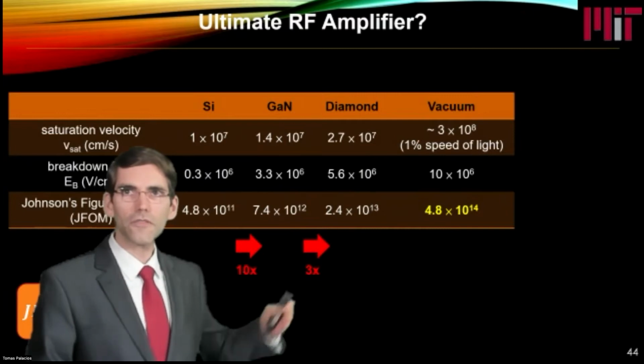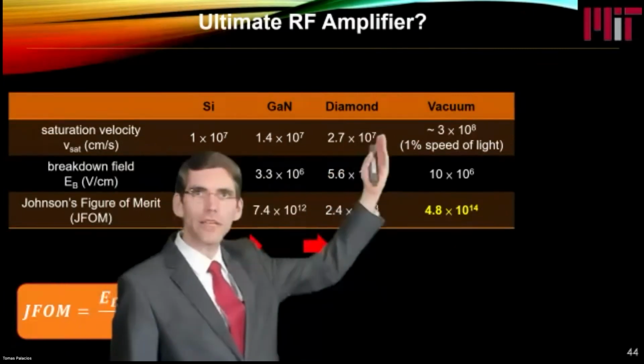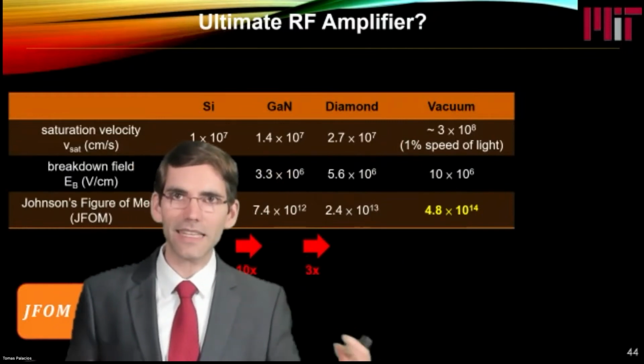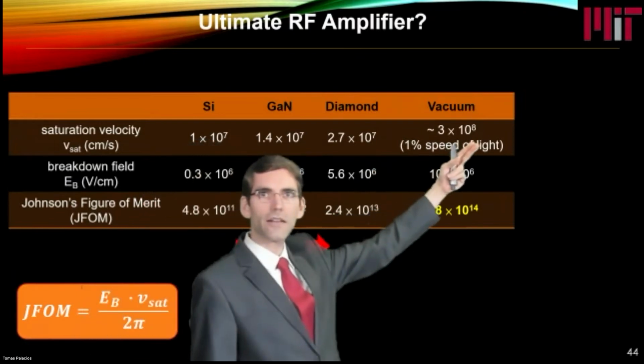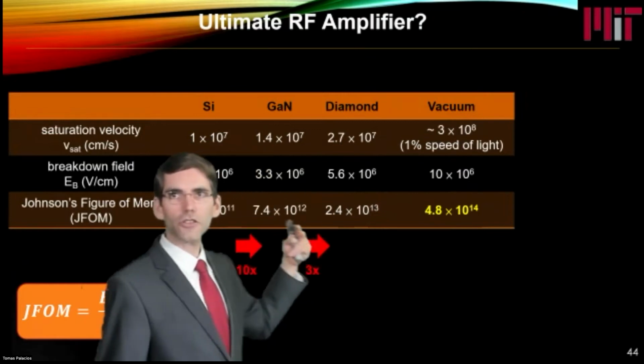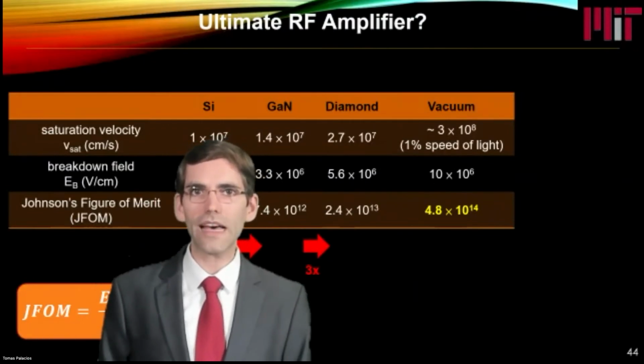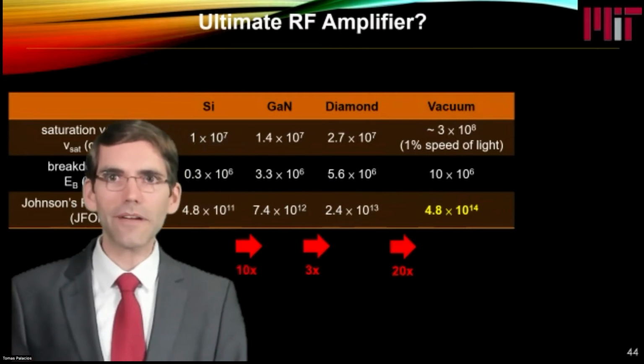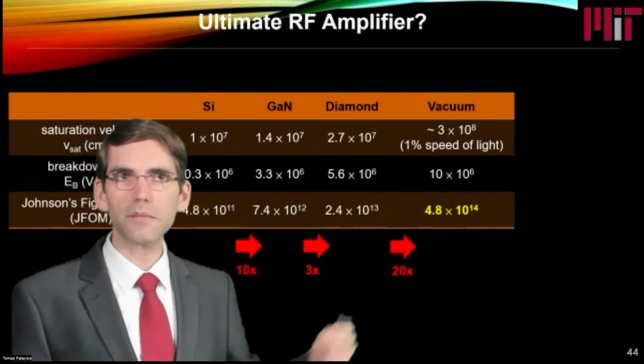Actually, if we could go from silicon to gallium nitride to diamond to vacuum, vacuum happens to be the best material for electron conduction. That's where electrons reach the highest velocities because there is no scattering. And it also shows extremely high breakdown fields because there is nothing in vacuum. When you combine all that, you get that vacuum devices should be roughly 20 times better than the best you can do with diamond. So let's make a transistor out of vacuum.